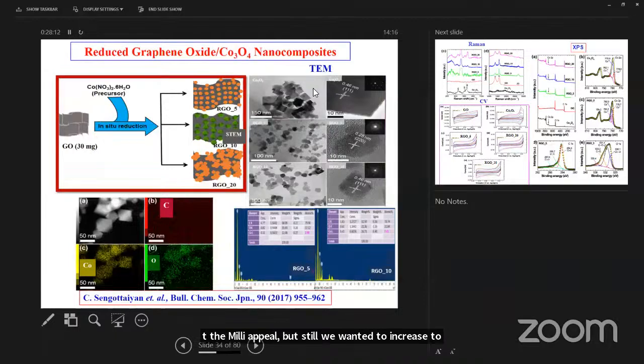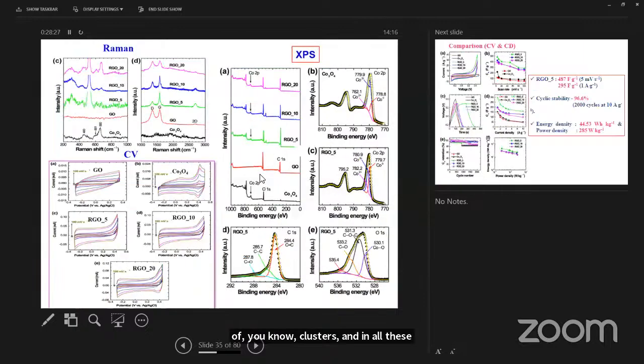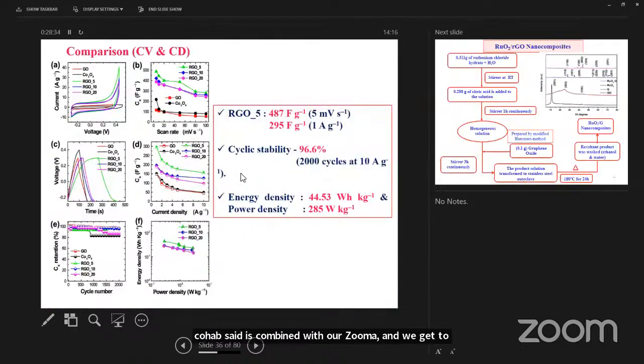This is actually RGO with cobalt oxide, and the cobalt oxide has the tendency to form different combinations, like spherical particles, trigonal shapes, and some kind of clusters. In all these forms, the cobalt oxide is combined with RGO, and we get a current density of the order of milliampere. For this electrode, the power density was estimated to be around 285 watt/kg, with an energy density of 44 watt-hour/kg. And the cyclic stability is also reasonably good, up to 2000 charge-discharge cycles at a current value of 10 ampere per gram, which is 96.6%.